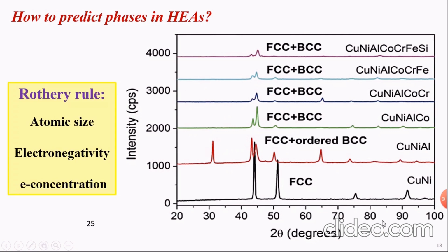Why? Because every element we add has a different atomic size, different electronegativity, and different electron concentration, and will affect the total electron concentration in the system. So every element you add to the high entropy alloys changes the type of solid solution formed. It can be a single solid solution or a double solid solution, ordered or disordered. It depends on the additives you add.